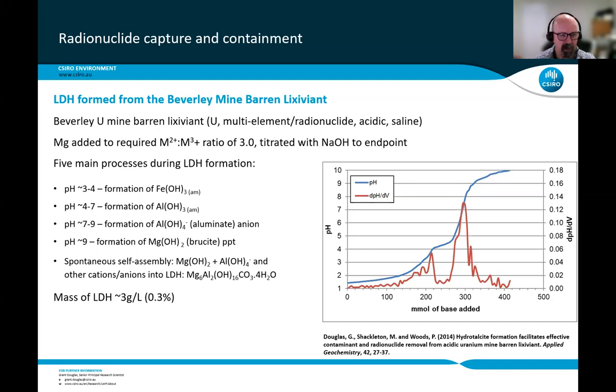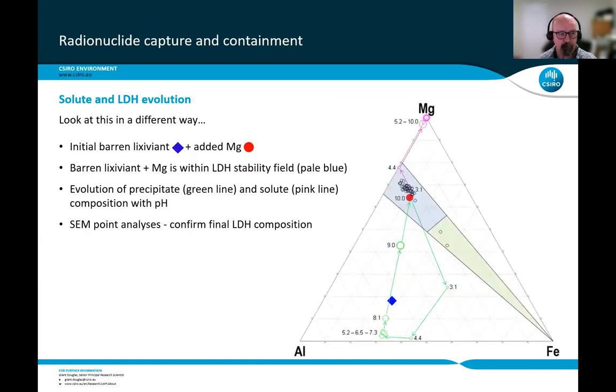So we've now got magnesium hydroxide and we've got the aluminate anion. And when you have those together, you get the spontaneous self-assembly of those, plus other cations, anions, and radionuclides into the layered double hydroxide here. Here, as I said, a 3 to 1, Mg6 to Al2 layered double hydroxide. Now, the other thing to note here is that the mass of this was around about 3 grams per litre, or about 0.3% by mass. You really are getting very small amounts of the layered double hydroxide. And again, that attests to the very high uptake capacity and the concentration factor that we've seen previously in the Beverley mine pit, and we'll see in a few moments here.